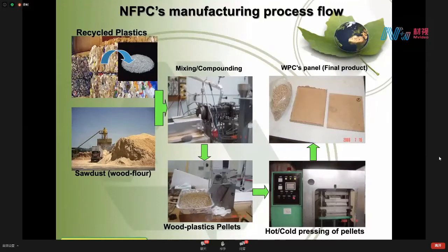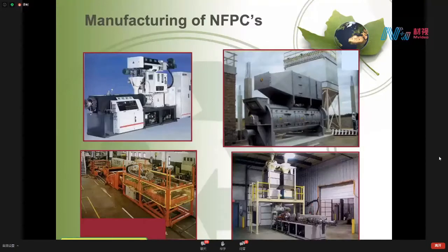This is the scheme of how to produce. We can produce these materials from virgin polymers or from recycled polymer. As in the slide now, recycled materials we collect and make pellets, and also the sawdust. One of the biggest challenges is that natural fiber absorbs water, so the water content must be dried to between 2 and 8%. After that, we combine them to make wood or natural fiber panels. This is the machine, the most important point, producing liquid wood, which we can process through plastic machines, and we deal with these materials as wood.